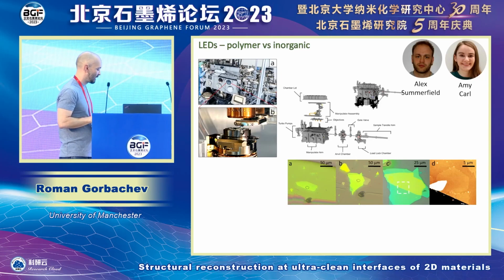polycrystalline material you buy. And so the most advanced step that we took is putting this whole technique into UHV, ultra-high vacuum. Here you can see a brief sketch. This chamber is about a cubic meter large, and it has all of the stacking stages. I think in total there are 11 stages inside that manipulate, exfoliate crystals, and stack them in ultra-high vacuum. If you choose to do polymers in UHV, it doesn't actually help. Well, it helps a little bit, but you can still see bubbles if you use polymers.